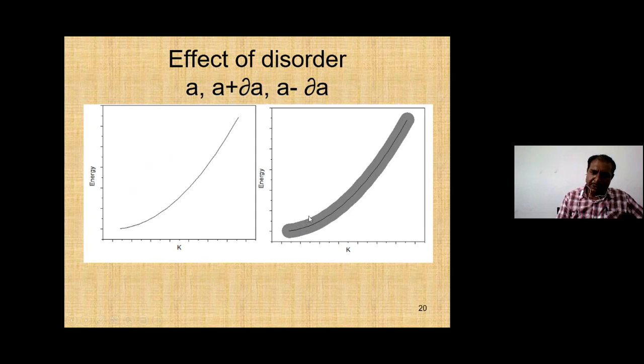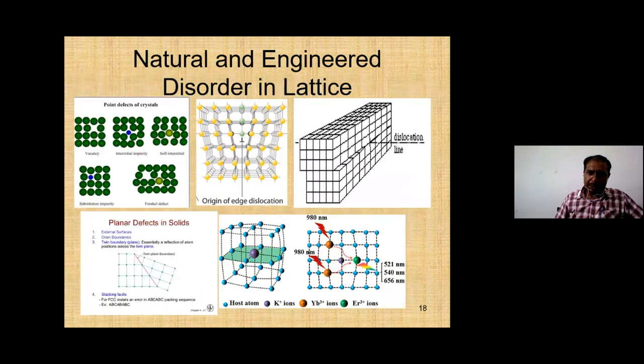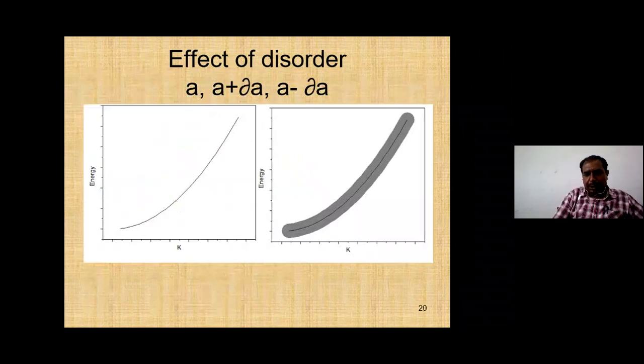unit cells are defect free. The order of the defects is very, very small, 10 raised to power 16, 10 raised to power 18 out of 10 raised to power 23. So it's really small. But you get some faint states in the energy as a result of this disorder in A. And why do you get the disorder in A? The disorder in lattice parameter is essentially due to various defects present in the sample. So defects give disorder in the value of lattice parameter, and this is reflected in the spreading of energy.